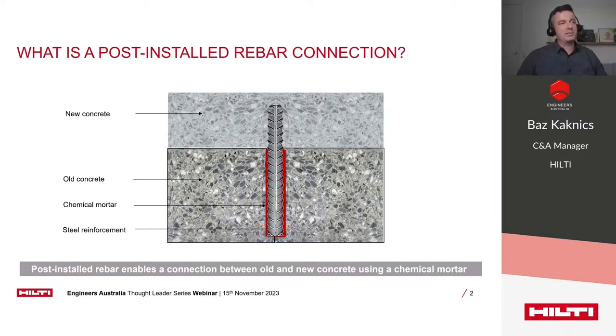The intention of installing bonded bars is to develop a monolithic connection between new and existing concrete elements, which we often refer to as concrete-to-concrete connections. This is achieved by drilling a hole into the existing concrete, which is then injected with a pre-qualified high-strength, usually special type of epoxy or vinyl ester product. After this, a cut-to-length reinforcing bar is inserted and left alone until the chemical is fully cured. The surface of the existing concrete is often roughened to improve the transfer of shear stresses between the new and the old concrete. And finally, the new concrete is poured, turning the two structures into one monolithic unit.